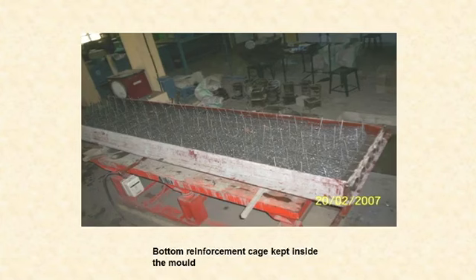The ferrocement bottom reinforcement cage with 8 mm diameter steel bars as skeletal reinforcement and 4 mm diameter transverse reinforcement, along with the stirrups and the 3 layers of chicken mesh, were placed. The reinforcement cage was placed over the cement mortar spread inside the mold. And here you can see the openings in the sides of the mold.